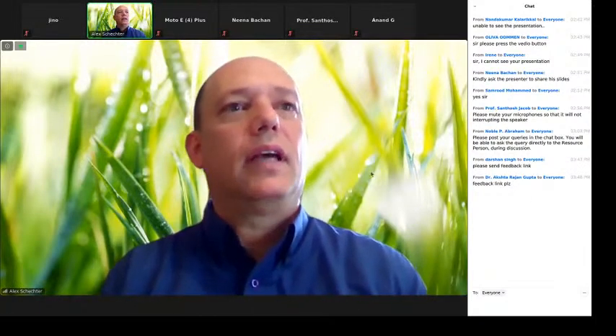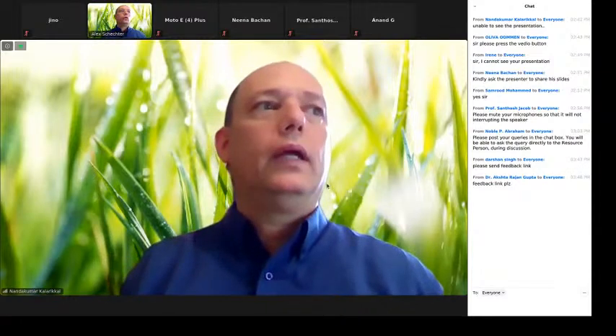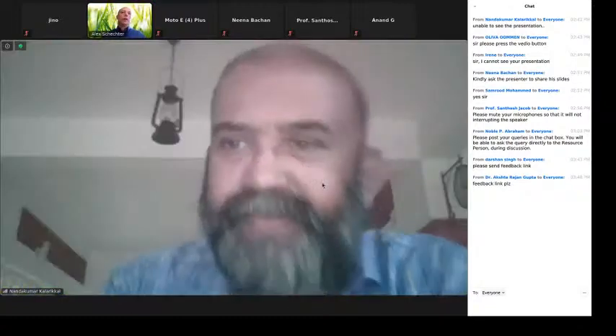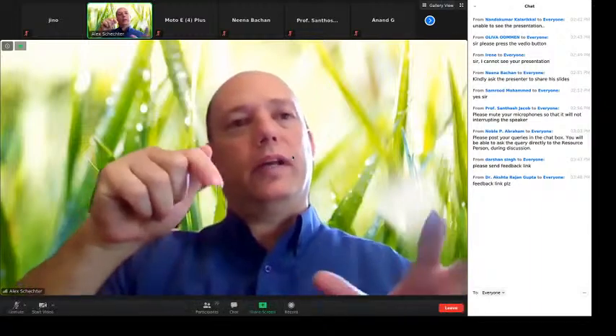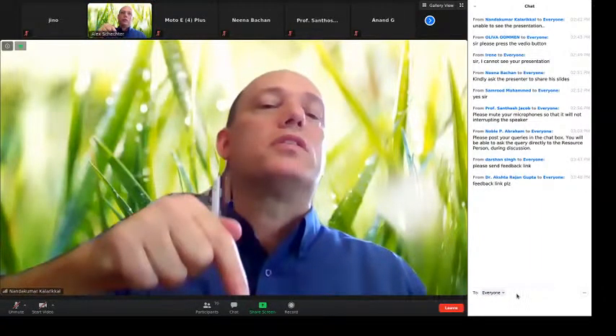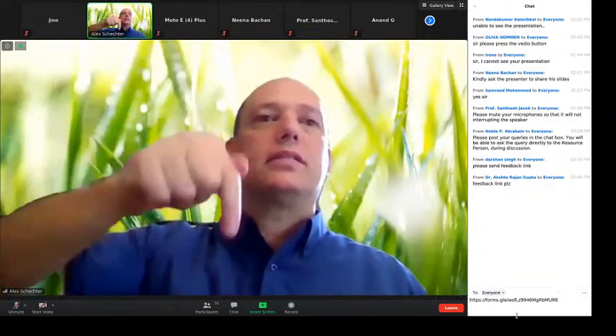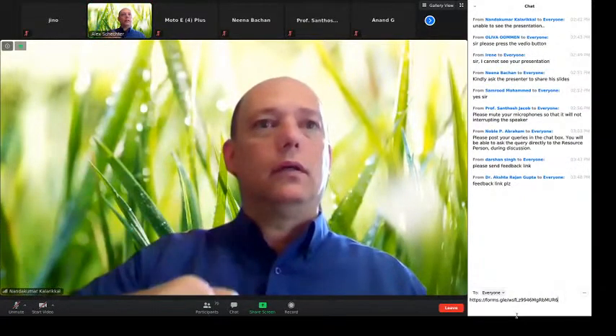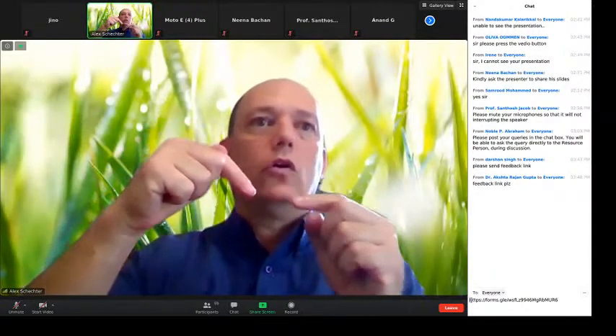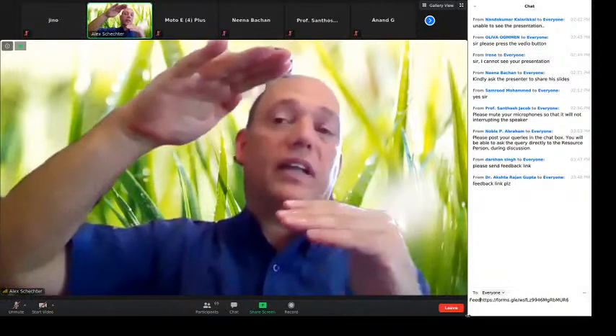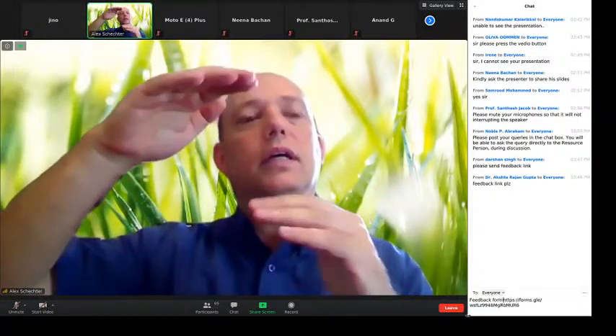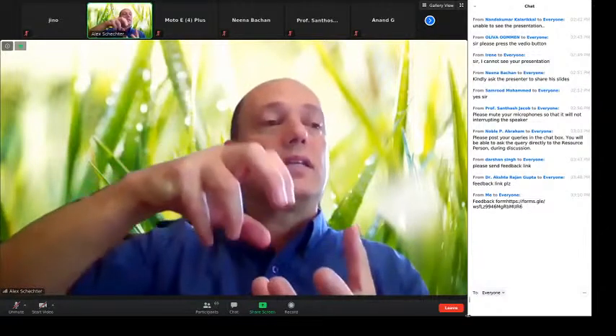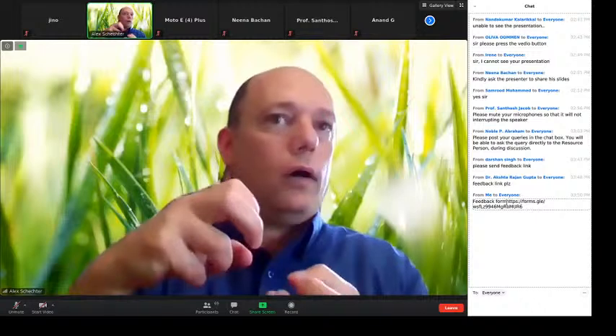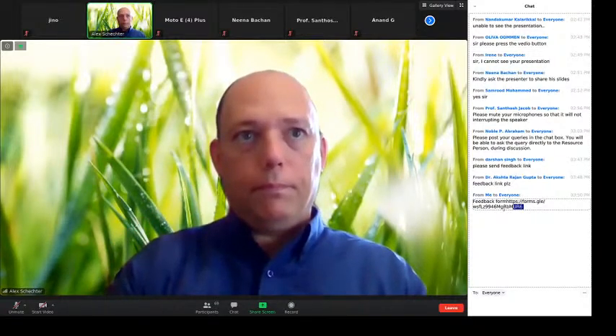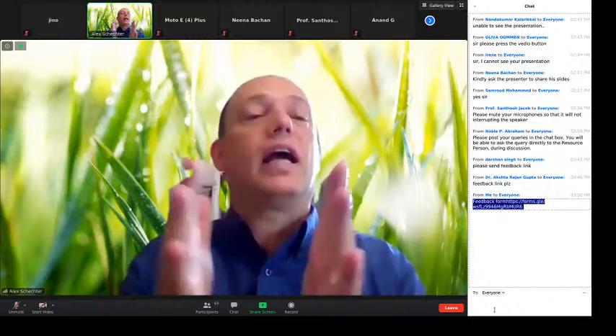Yes. The way we did it is we took a standard solution that we prepared of hydrogen peroxide, at different concentrations, and we placed it in the tip without running any current or anything. We just placed the tip as if it was under measurement. Now we use the laser to provide the Raman signal, shining at the top of the gold tip. As the tip approaches, or as we stop, let's say at 5 nanometers away from the surface, the signal has a certain intensity, which is proportional to the concentration of the peroxide standard solution that we use. So that was the calibration curve.